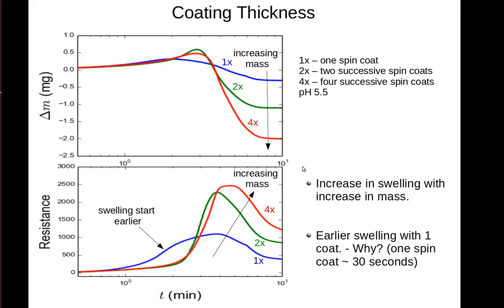QCM can also be used to measure the effects of coating thickness. Here we see mass versus time, for different amounts of mass on a crystal. 1x, 2x, 4x correspond to the number of times of spin coating on the crystal. As expected, as the mass of the polymer on the crystal increases, we dissolve more mass during the dissolution run.